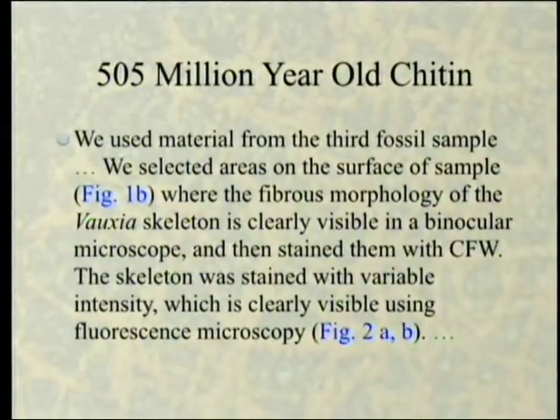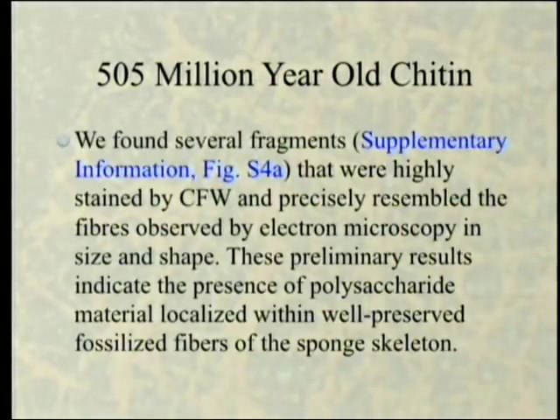We used material from the third fossil sample. We selected areas on the surface of the sample where the fibrous morphology of the Vauxia skeleton is clearly visible in a binocular microscope. You saw the picture, and then stained them with CFW. The skeleton was stained with variable intensity, which is clearly visible using fluorescence microscopy, figure 2A and B. We're going to see figure 3, which shows some of that staining that they did. We found several fragments, supplementary information, that were highly stained by CFW and precisely resembled the fibers observed by electron microscopy in size and shape. The staining looks like it's on the stuff. These preliminary results indicate the presence of polysaccharide material localized within the well-preserved fossilized fibers of the sponge skeleton.